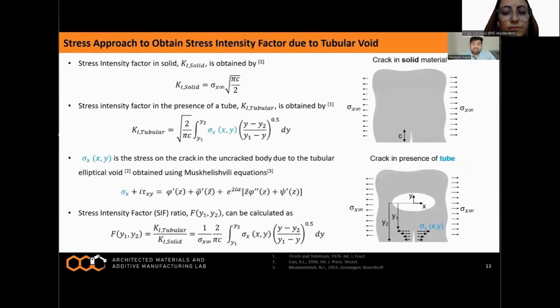For a better understanding of the toughening mechanism, we looked into the theoretical analysis of stress intensity factor and stresses at failure of crack in the tubular architected material. Stress intensity factor is used to predict the stress state near the tip of the crack or notch caused by the far-field stress, that is sigma x infinity. The stress intensity factor in the presence of a tube can be defined in terms of the stresses on the crack in the uncracked body due to the tubular elliptical void, as shown by this blue sigma x. Now, sigma x can be obtained using the Muskhelishvili-Kolosov equation.